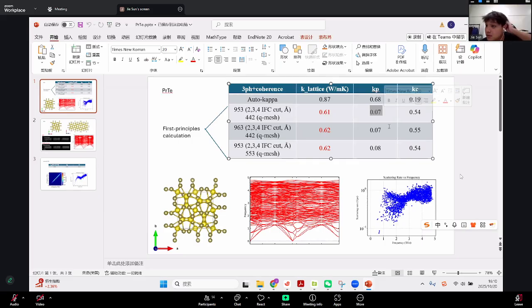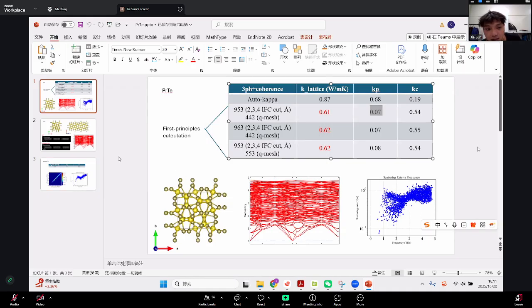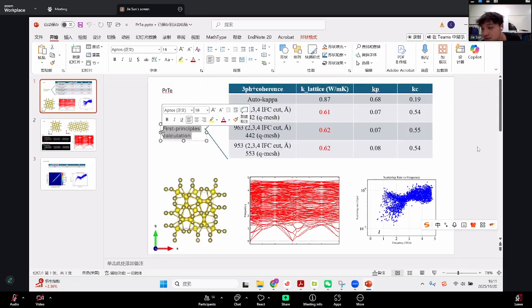I think the number of supercell structures is small. Because this structure is very complex, I think maybe we need to generate more supercell structures to fit for the force constants. Here I only used the Monte Carlo like random displacement method to generate 50 structures, then fit for their force constants. Because the first principles calculation is heavy, I only generate 50 structures.